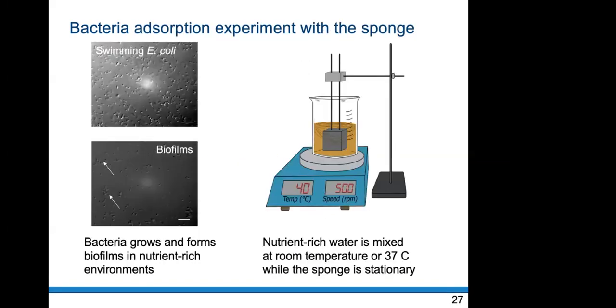Here, the way I did the experiments is I took this protein water and mixed it at different RPM, about 100 to 500 RPM. I also maintained the temperature depending on the physiological conditions of the bacteria, anywhere from room temperature to 37 degrees Celsius.